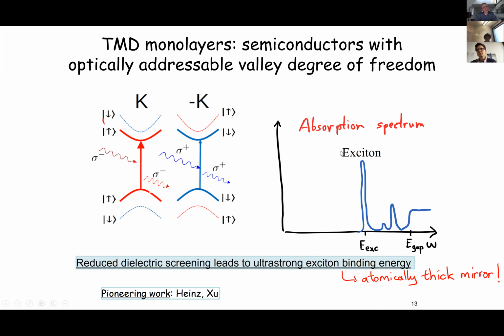Now, for the same reasons that I mentioned, the small effective mass and weak screening, the absorption spectrum of these materials shows very pronounced, strong excitonic resonances with binding energy that is more than an order of magnitude larger than that of gallium arsenide. Actually, without a suspended layer, it will have a binding energy that is almost two orders of magnitude larger. And basically, because of this strong binding, leading to a small Bohr radius, the excitons have very nice properties. For example, if you shine light resonantly on the exciton transition, you can get a very high degree of reflection approaching 90%. So these materials are essentially atomically thick mirrors.